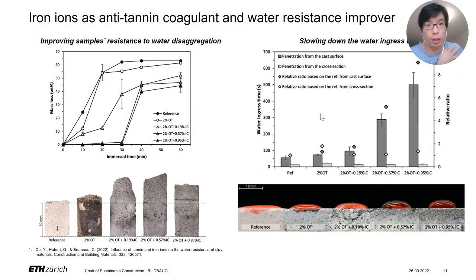We also did some water resistance tests of the sample. On the left is a dip test. We can see that after putting in this additive solution, the sample is more water resistant. Here we can see a delayed fracture time of the immersion part. We also see the sample surface is more intact after 1 hour of immersion. So tannin combined with iron chloride can provide some protection, or increase the sample resistance to water disaggregation.